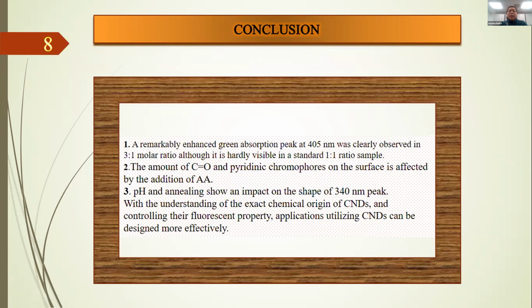From the above study, we can conclude that the green absorption peak at 405 nanometer is clearly observed in the 3:1 molar ratio sample, but it is hardly visible in the standard 1:1 ratio sample. The amount of the C=O and pyridinic chromophore on the surface of the CND is increased by the addition of acetic acid. pH and annealing also show an impact on the shape of the 340 nanometer peak. With this understanding about the exact chemical origin of carbon nanodots, we can control the fluorescent property, and applications utilizing the CNDs can be made more proper and efficient.